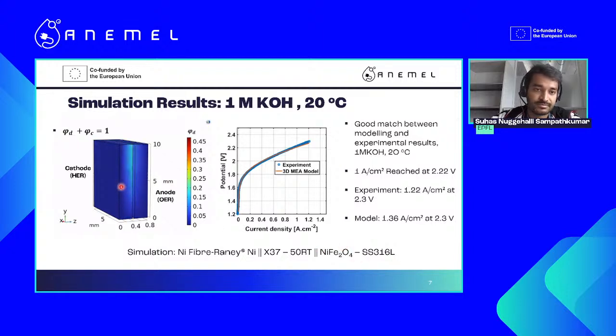And here what you see is the evolution of gas fractions in the cathodic and the anodic chamber, which pretty much follows the stoichiometry. As you can see, the hydrogen side has a larger gas fraction compared to the oxygen side. Well, the continuous phase, which is phi c here, is the liquid phase, and the dispersed phase is the gaseous phase. They sum up to 1, and this is how the gas fractions were calculated and evaluated from bottom to top. And you can see that the gases tend to go towards the exit of the MEA simulation.